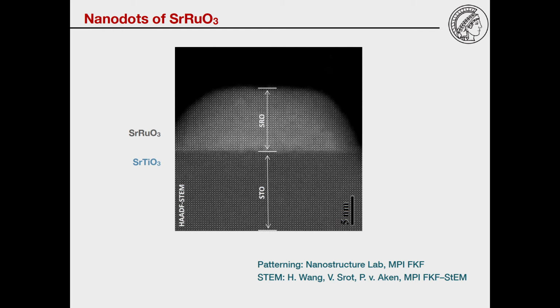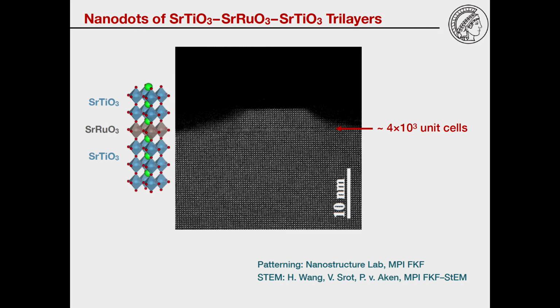Here's one example: strontium ruthenate grown on strontium titanate, a quantum dot. Strontium ruthenate is a ferromagnet. What you're seeing here is a TEM cross-section of a real dot, and the points in the dots are individual atoms. So in this sample, the number of dots on the wafer is larger than the number of atoms in one dot. And it turns out, to my huge surprise, that if one fabricates these dots and makes them smaller and smaller, you would expect that they deteriorate. But it turns out that the magnetism gets better and better. T_C gets higher and higher the smaller it gets.